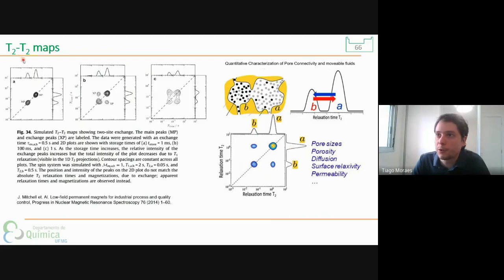Also, we have T2 maps. In both dimensions here, we have the T2 relaxation times. And these applications are interesting when you want to see, for example, if the pores have connection between them. If they have connection, the fluid can come from here to here. And this will result in some peaks off the diagonal in these maps. So for example, here, a system where there is no connection of the pores, and here there are bigger connections between the pores.